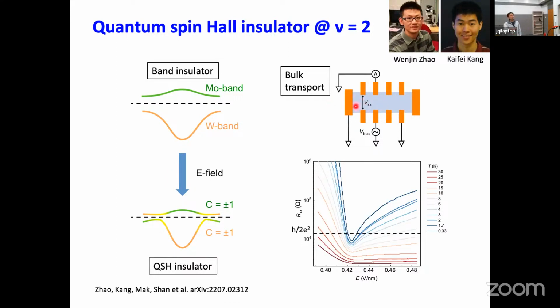And when we measure the 4-point resistivity in this case, we measure the voltage drop across these 2 electrodes. When we do that, you can see that the resistivity as a function of the electric field after the band inversion keeps going up with decreasing temperature, right? When we access the bulk resistivity of the material, it acts like a proper insulator. It does not show a plateau anymore. It just keeps going up with decreasing temperature.